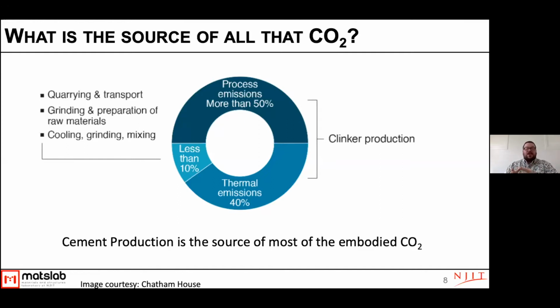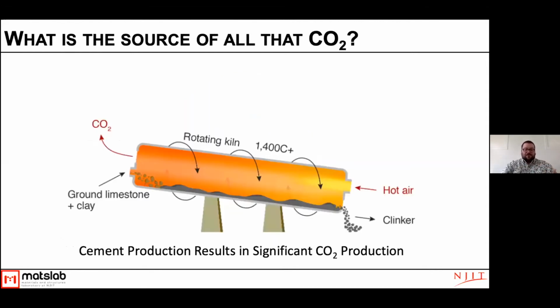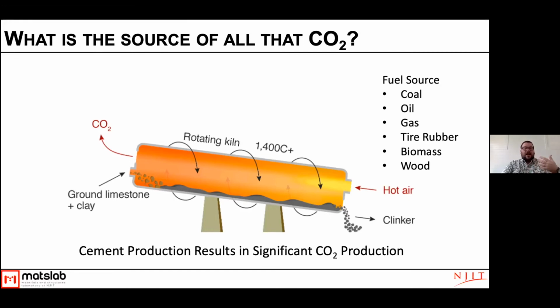And so this is what Sue talked about a moment ago, where we actually have to break down limestone. When we make cement, it goes into a rotating kiln. This is usually around 300 or 400 feet long. It's quite a large facility. We don't have any cement production here in New Jersey, but there's some in New York and Pennsylvania. We put our raw materials in at the top. We have a heat flame coming down at the bottom, and those materials, as they move through the kiln, heat up and change.